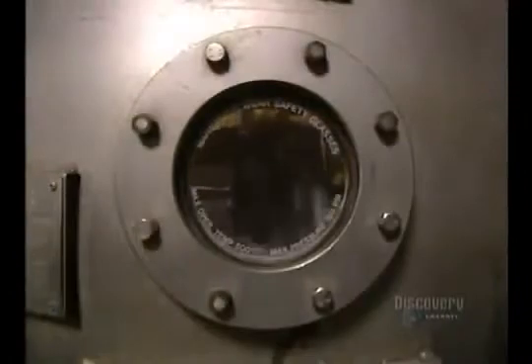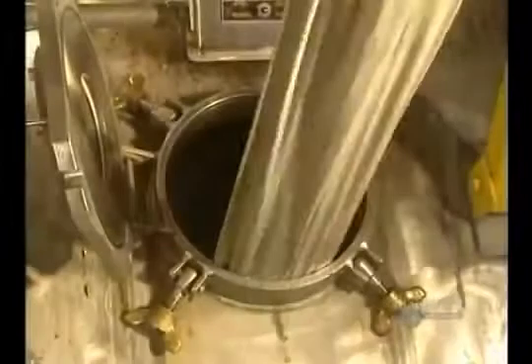Now it's on to dyeing. This is done with jets. Up to 12,000 meters of fabric are placed in clean water into which colorants have been added. The solution is heated and the fabric soaks here for about 6 hours. Then it will be rinsed in lukewarm water.